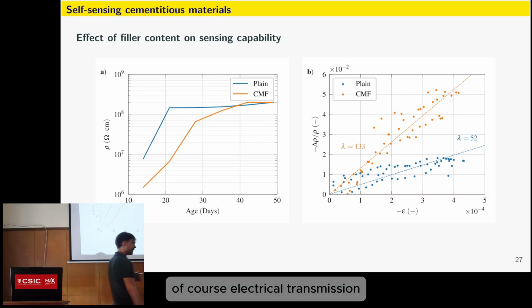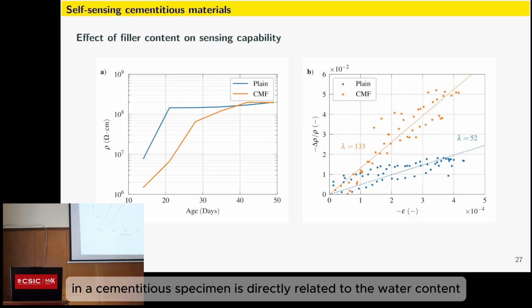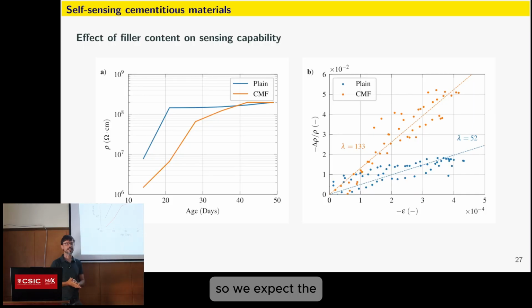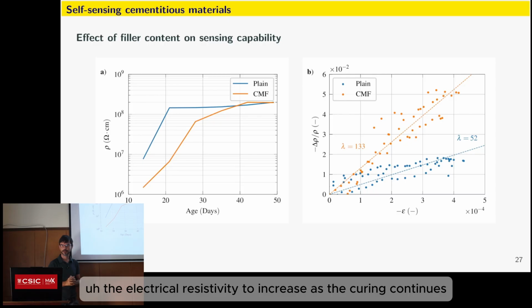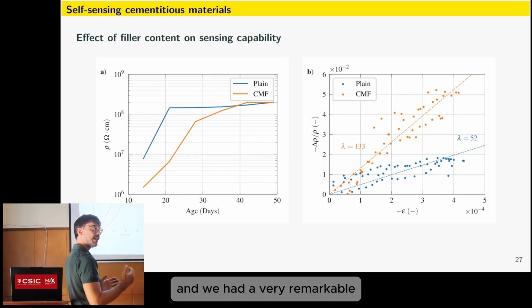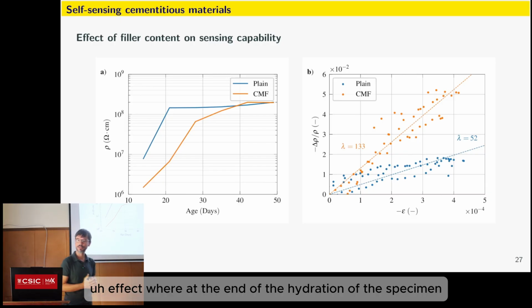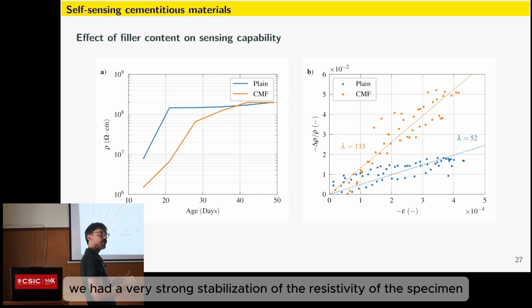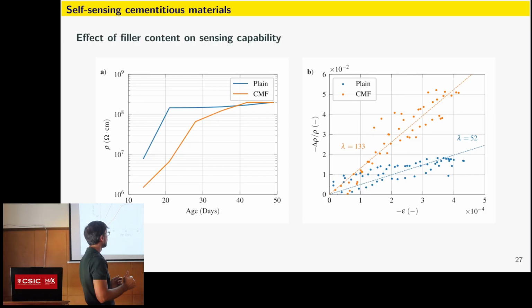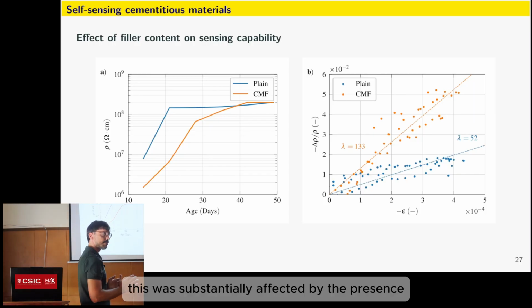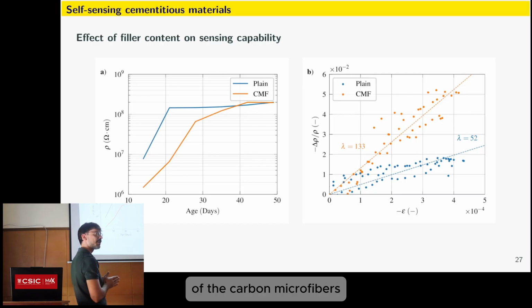Of course, electrical transmission in a cementitious specimen is directly related to the water content. So we expect the electrical resistivity to increase as the curing continues. And we had a very remarkable effect, where at the end of the hydration of the specimen, we had a very strong stabilization of the resistivity of the specimen. This was substantially affected by the presence of the carbon microfibers.